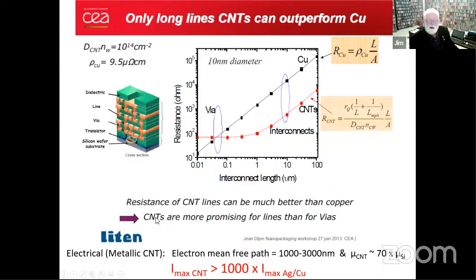So the two results of this is carbon nanotubes are more promising for lines like this, i.e. for power delivery, than for vias where you're looking for low resistance for signal propagation. But you do get a very much higher maximum current density. But these measurements in the literature, if you look at them, they're all for DC.